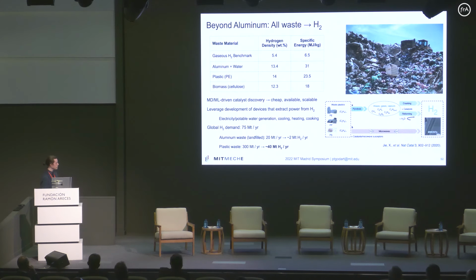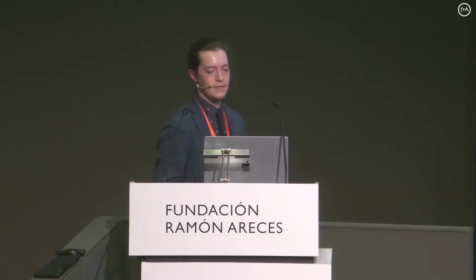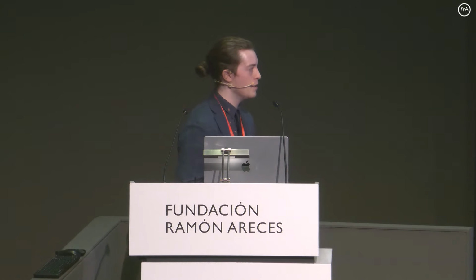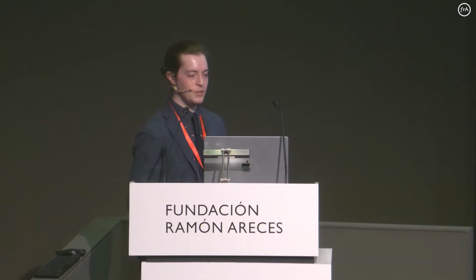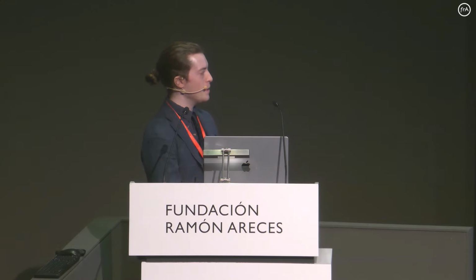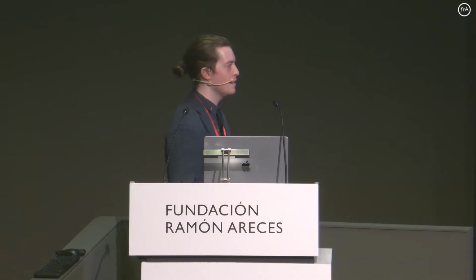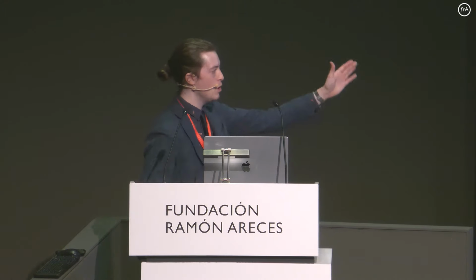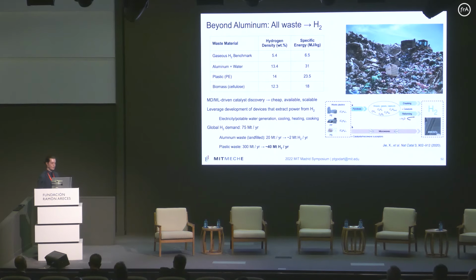And so if we look at the global hydrogen demand, which is about 75 megatons per year, and we look at all of the aluminum waste that's currently landfilled, that's about 20 megatons per year, or about 2 megatons of hydrogen per year. So it's a very small percentage of the global hydrogen demand. But if we can start tapping into some of these other waste streams like plastic, plastic alone would account for about 40 megatons of hydrogen per year, which is more than half of the global hydrogen demand. So I would say that this fact alone indicates to me that looking at generating hydrogen from plastic warrants more research going forward.